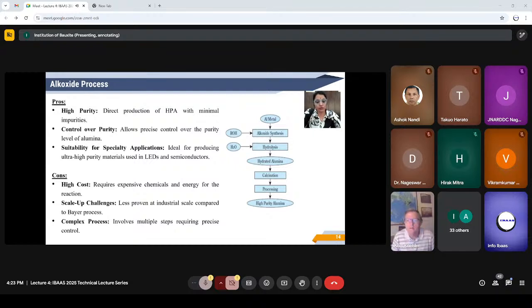So once we purify, then the alkoxide goes under the hydrolysis process. It means it will react with water to form aluminium hydroxide. And then this is followed by calcination, where the hydroxide is heated at high temperature, above around 1000 degrees Celsius, to yield high purity alumina.